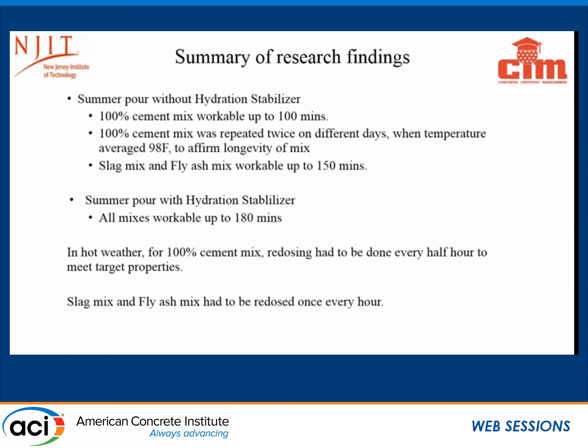So, the summary of the findings. In the summer, as expected, the workability was not going to be as long as in moderate temperature. We pretty much had to redose with stabilizer and high-range water reducer about every half an hour. In the case of the 100% Portland cement, we actually did it twice to get a more average result and to determine the effects again. The slag and fly ash mixes were workable up to 150 minutes. The 100% cement, not so much. It started setting up much earlier.